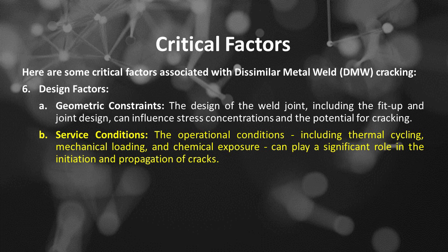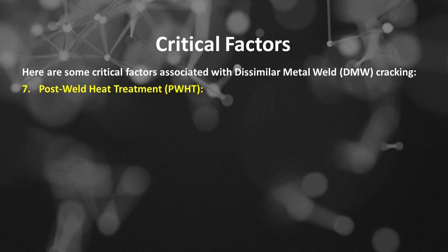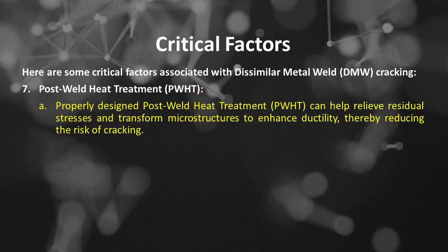propagation of cracks. Number 7 is post-weld heat treatment, or PWHT. Properly designed post-weld heat treatment, PWHT, can help relieve residual stresses and transform microstructures to enhance ductility, thereby reducing the risk of cracking.